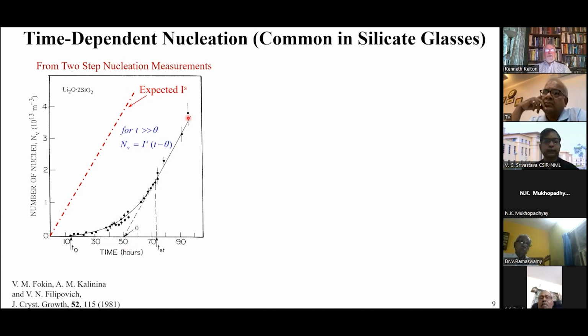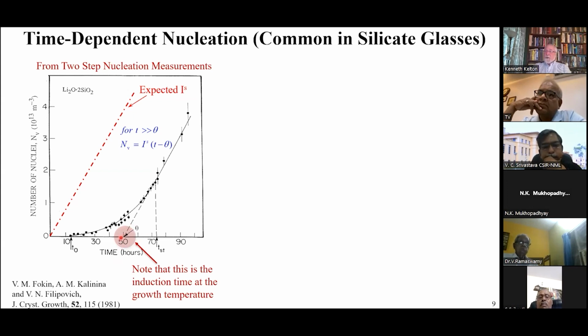It almost, to first order, looks as if you were far beyond what is called the induction time, which is the extrapolation of the steady state rate back to the time axis, and it's called theta. It almost looks as if the number of nuclei would be the steady state rate multiplied by the time t minus that induction time. That's a very low order, but that's what it looks like. This induction time is going to be critical, and I'll talk about that in the next slide. And this is a technical point, but one that's often overlooked when people are making these measurements in the silicate glass community. This is the induction time at the growth temperature, and that gets more complicated, but it's an important thing to know if you're going to be trying to use this to make some measurements of the kinetics.